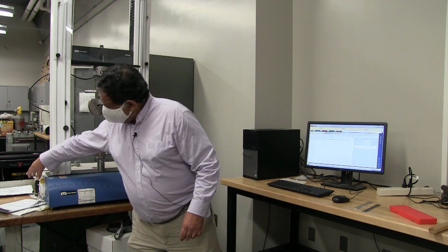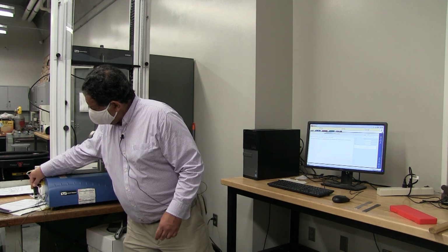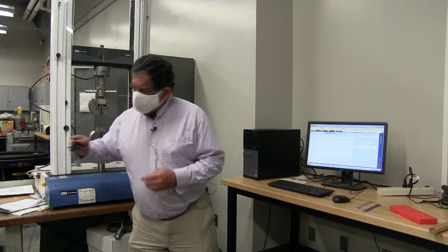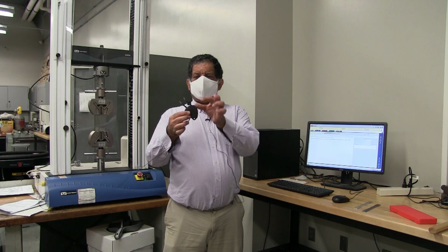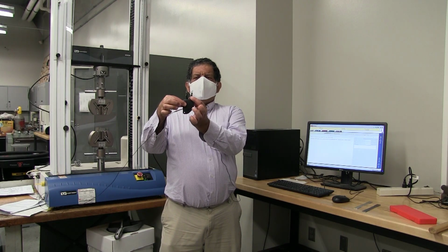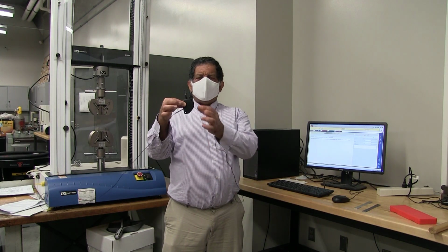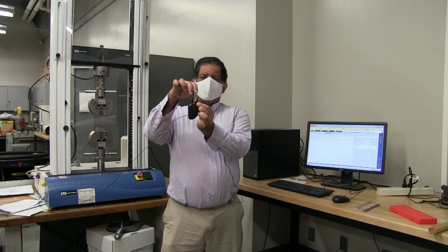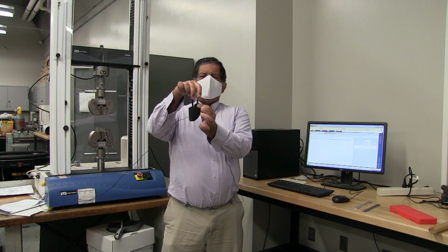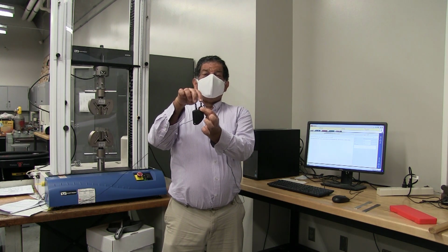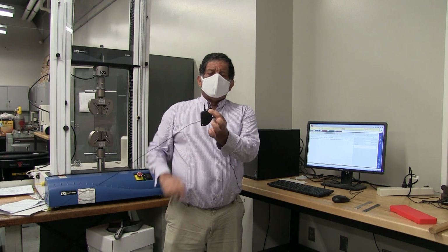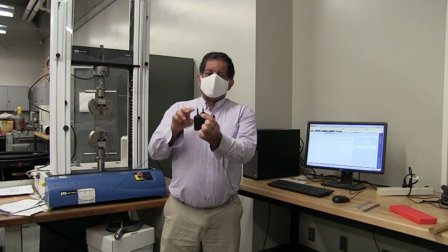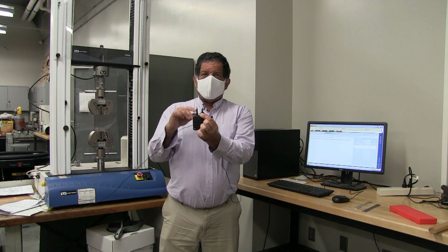So first I'm going to calibrate the extensometer, and in order to do that, I press these 2 buttons together. What pressing those 2 buttons together does is fix the separation between the knife edges on the extensometer at exactly 1 inch. So then when I do the calibration, it knows that this is exactly 1 inch, that's the starting point.